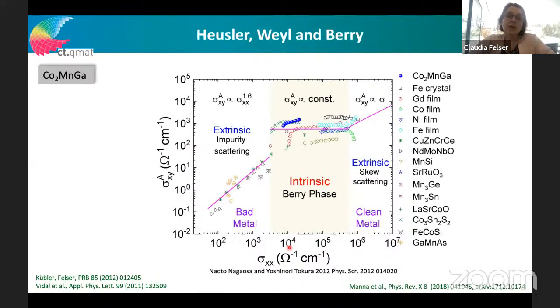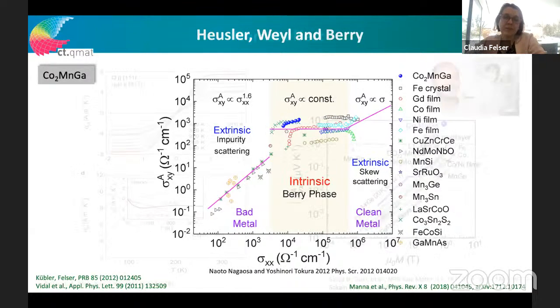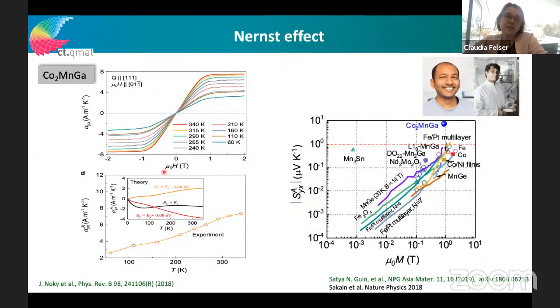So the spintronic community would immediately ask, did you really look? There are also extrinsic contributions to the Hall effect, and they are even related to the Berry phase. And indeed, if you look here in this famous diagram, you see that Co2MnGa lies here in this intrinsic area. So you can also measure it as a function of temperature, so that mainly the intrinsic properties play a role. We also measured the Nernst effect in this material, which is really large. If you see here the value of 8, and if you see it as a function of temperature, it increases even above room temperature.